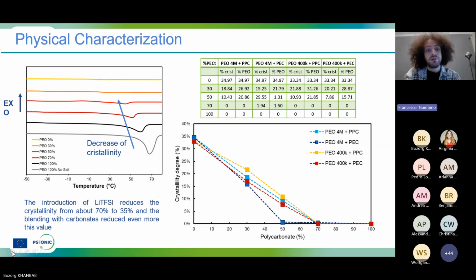Also, from DSC, we were able to determine the crystallinity of all of our membranes. We can see that there is a constant decrease of crystallinity of the polyethylene oxide-based polyelectrolyte. When LiTFSI is added, there is a reduction of crystallinity from 70 to 35%. But when we added our polycarbonate, there is a constant decrease of the peak of the crystallinity, indicating that the membrane is becoming more and more amorphous. In fact, at around 50% addition of polycarbonate, we had a residual crystallinity around 8%, and any further addition resulted in a completely amorphous membrane, with blend membrane with polyethylene carbonate displaying a slightly lower crystallinity than membrane with polypropylene carbonate. Next slide, please.